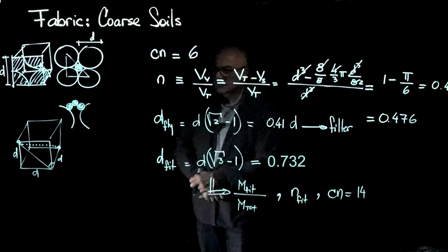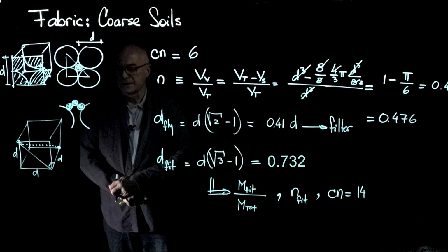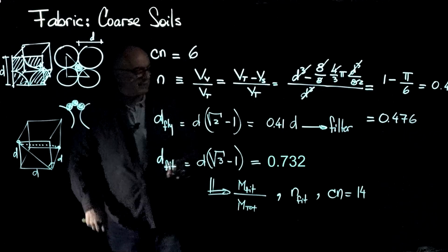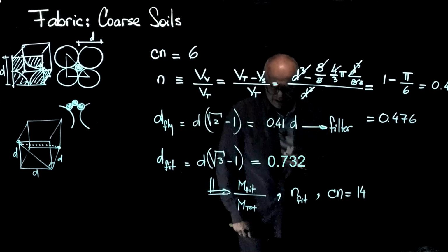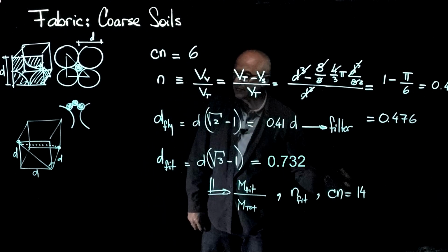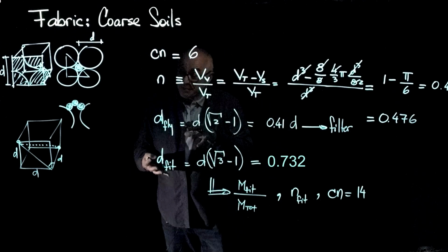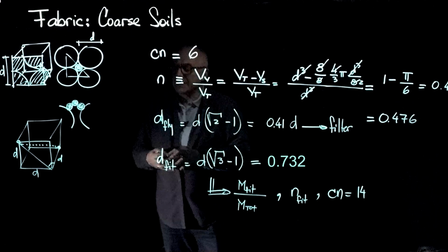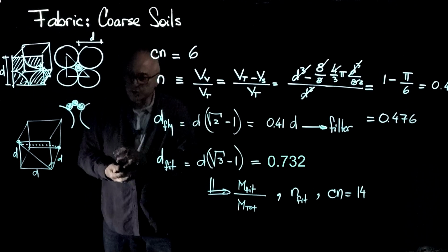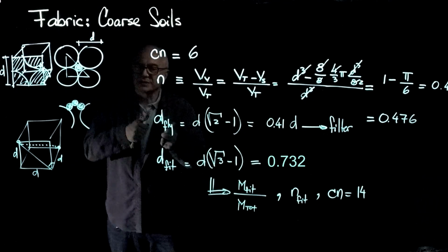And now something very important has happened. By being able to position particles inside other particles, I have dramatically reduced the porosity, I have changed the grain size distribution, I have changed the coordination number between particles. There will be much more friction trying to shear this, and because the packing density has become very high, in any shear, particles will not be able to fall in the voids, particles will have to expand. So I have decreased the porosity, and I'm going to cause an increase in dilatancy.